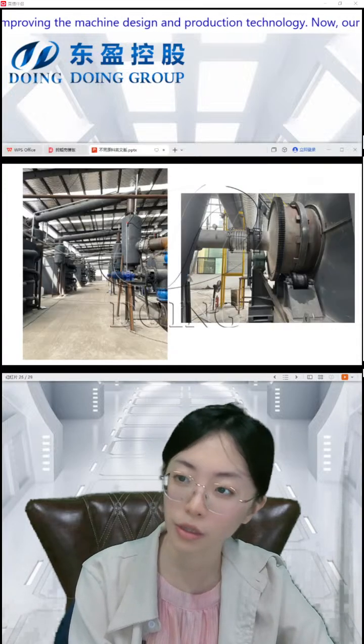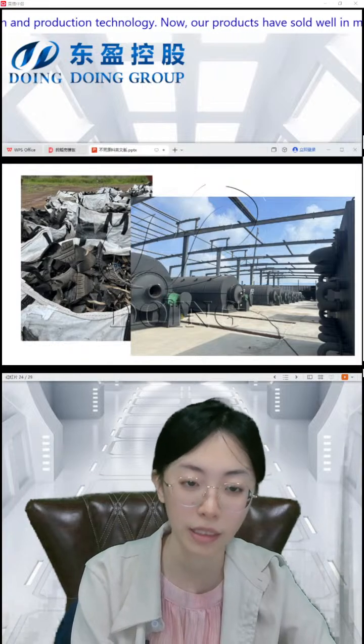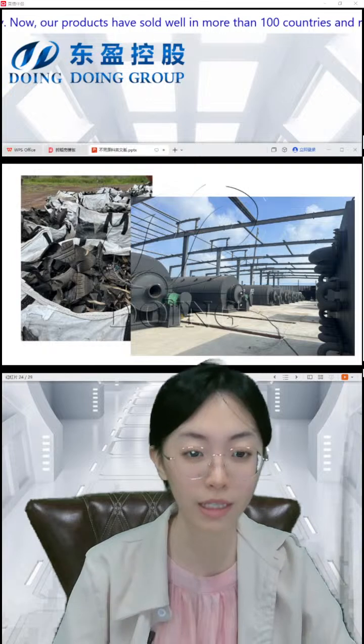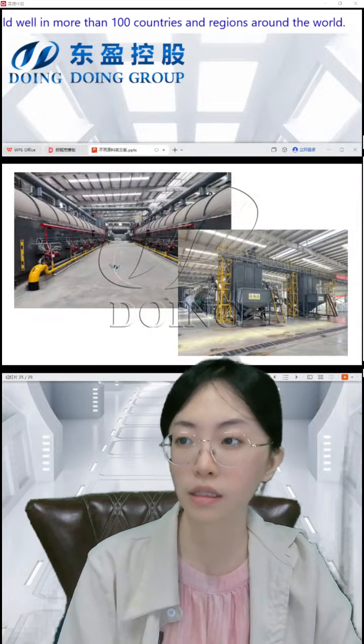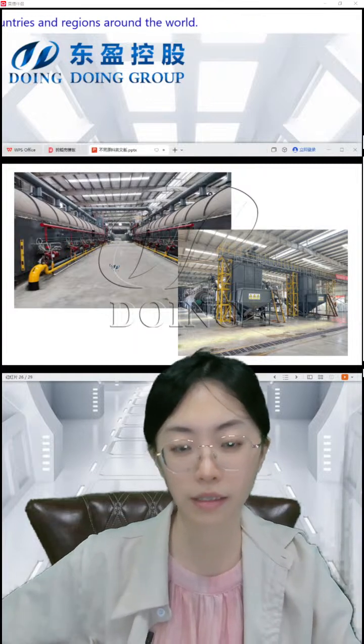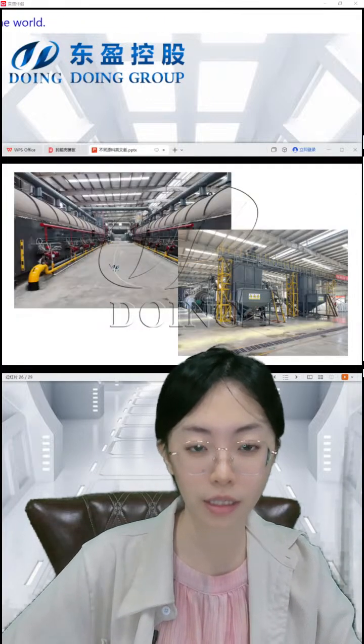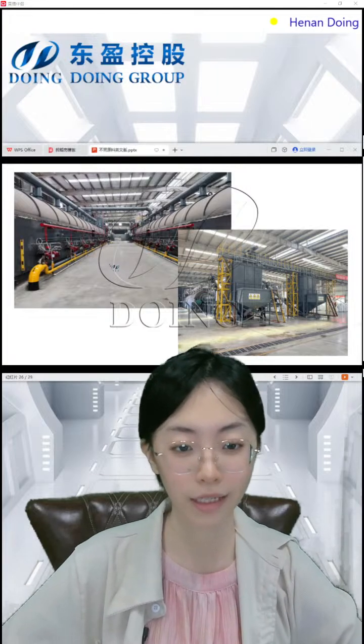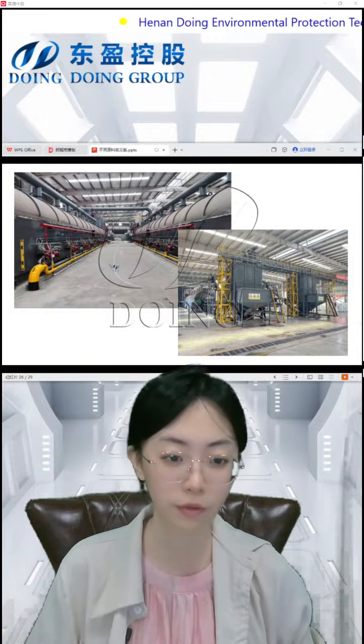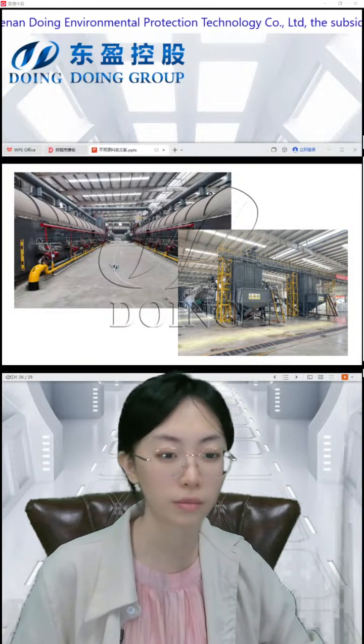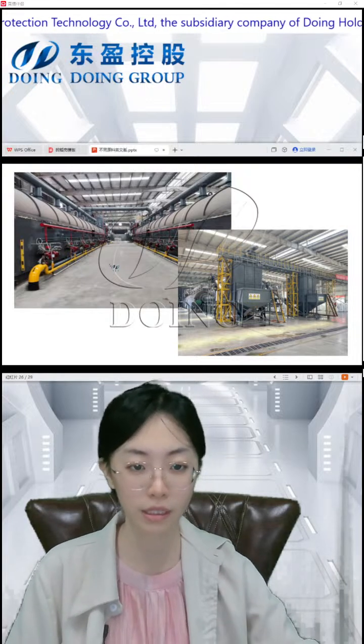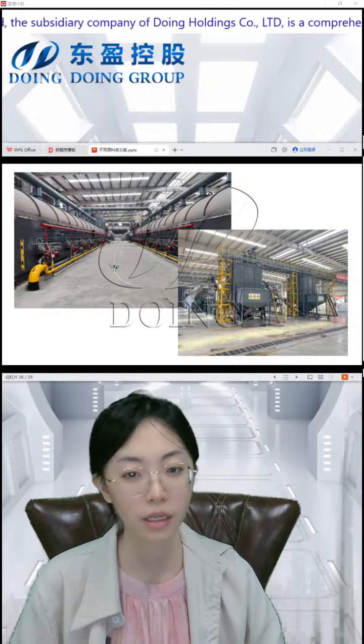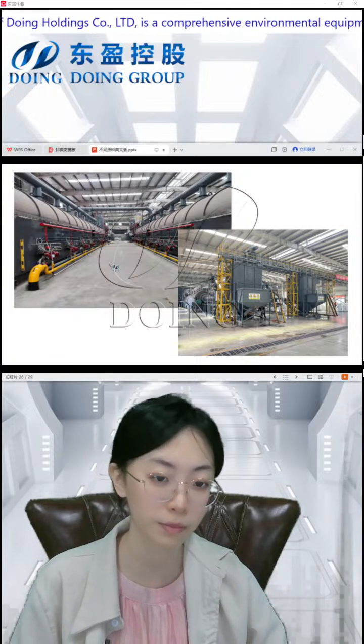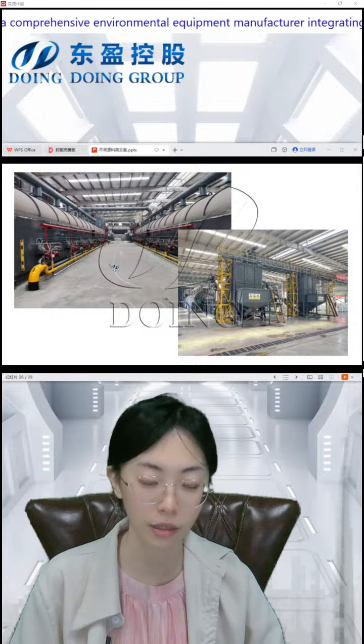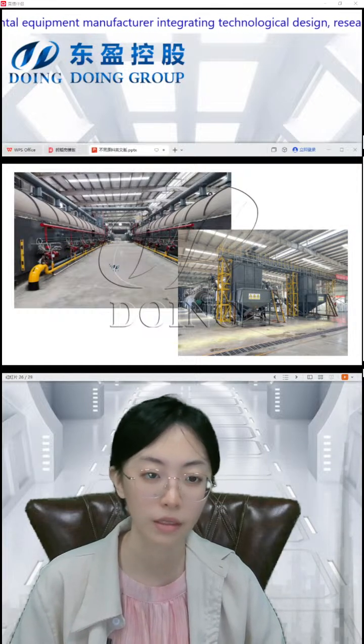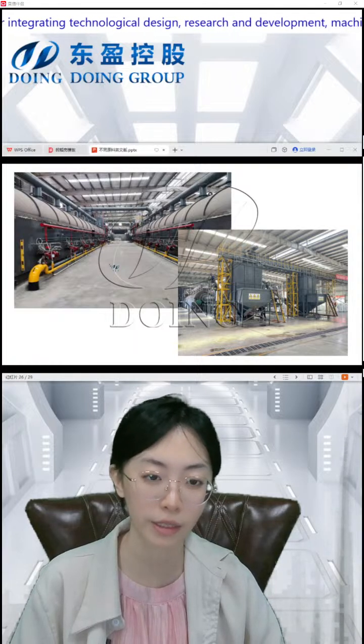These two pictures also show the batch type pyrolysis plant. The efficiency is one batch per day. And here is the fully continuous pyrolysis plant, which has a much higher efficiency. It can work 24 hours without stopping, and can work 45 to 60 days continuously. So most of our customers nowadays choose this fully continuous pyrolysis plant. It's much more environmentally friendly because it has a sealed design for the feeding system and the discharging system, so we don't have carbon black dust during the application.